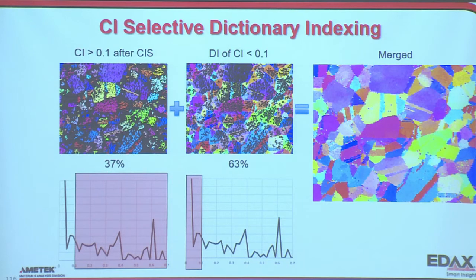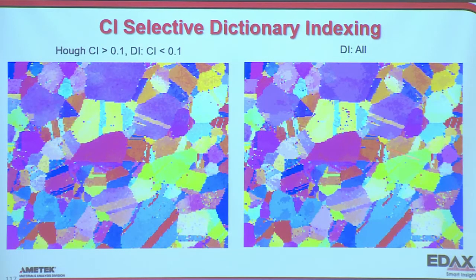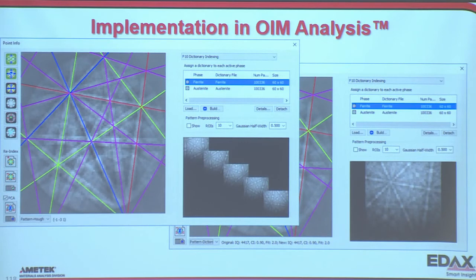37% of it is relatively decent CI data, 0.1 CI. And the data less than that is 63%. So I do 37% with the Hough and 63% with the dictionary, and I get a nice data set. And in fact, when you merge it together, it really is really good. It seems to actually be a little better than dictionary by itself. So I really like this technique, and it saves us some time, but gives us the benefits of both techniques.